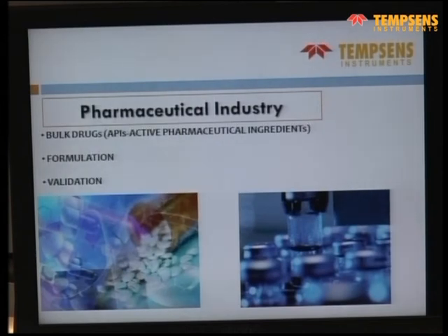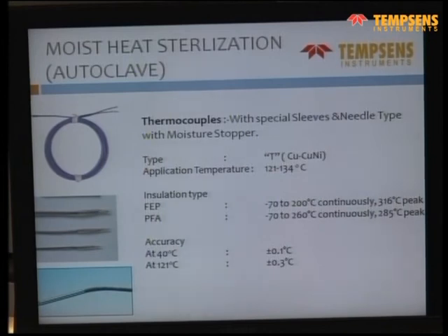In the pharma industry, there are various applications. They are normally low temperature applications. Normally in pharma industries, we use either a T-type thermocouple or an RTD, and the J-type thermocouple is normally used in the plastic industry. In the pharma industry, thermocouples are used in autoclave applications for bulk drugs. Here the main requirement is through the sensor. As you see the ring, it's not just the normal wire or compensating wire. We use thermocouple wires, insulated with Teflon in this case. So even with high pressure, the water should not come out from the other side. That's the application in the pharma industry.